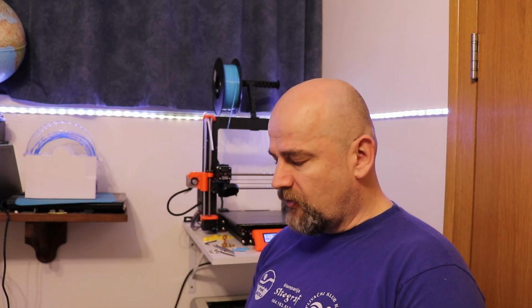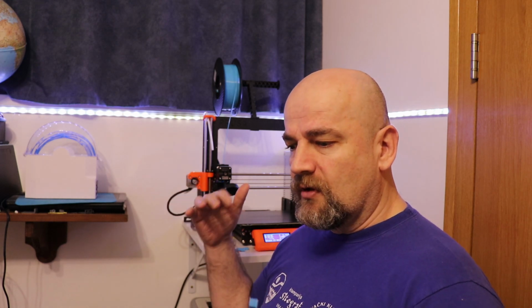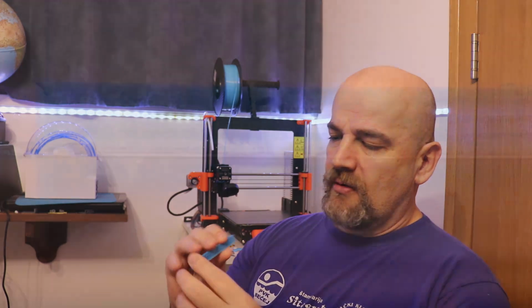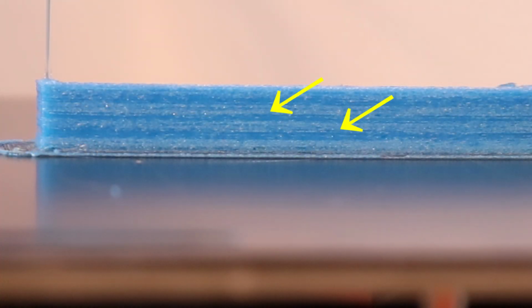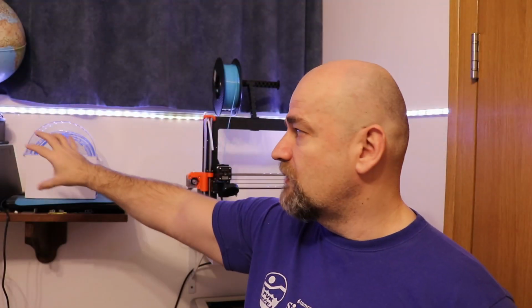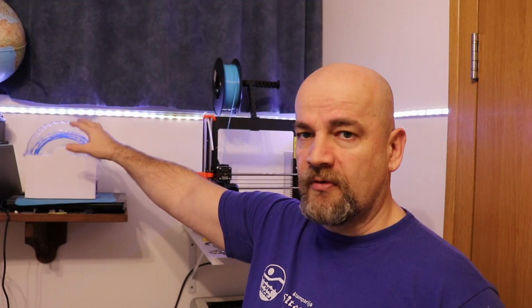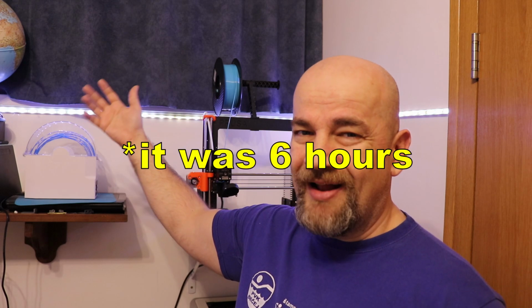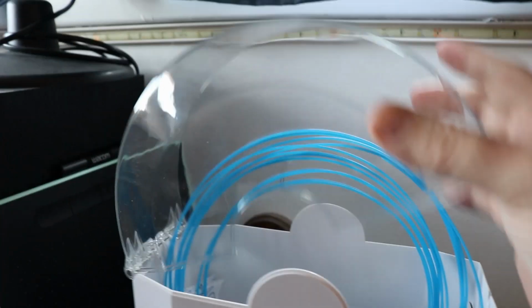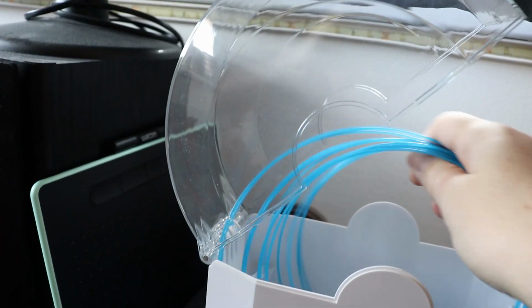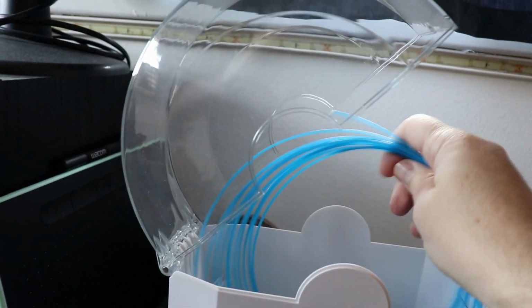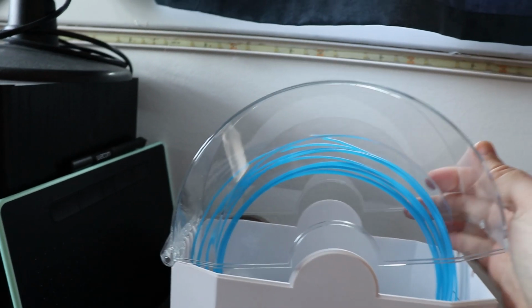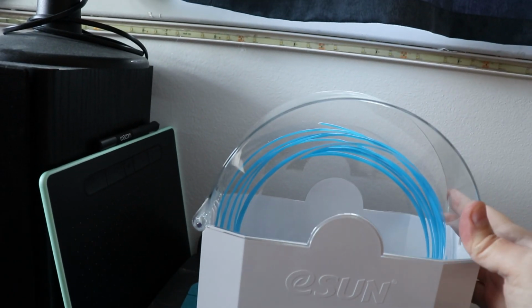Now one more thing I want to try, because I noticed that those short crack sounds appeared only periodically, and I can see those lines on these test specimens. I noticed the temperature is very different at the bottom and the top of the box. So what I did, I dried for another 12 hours and I slowly rotated the filament inside the drying box every hour or 2 hours. I hope now it will be dried more evenly, so I will try to reprint this specimen again.